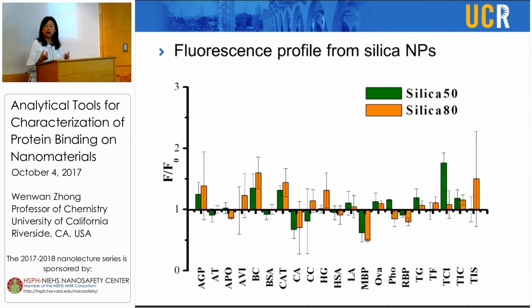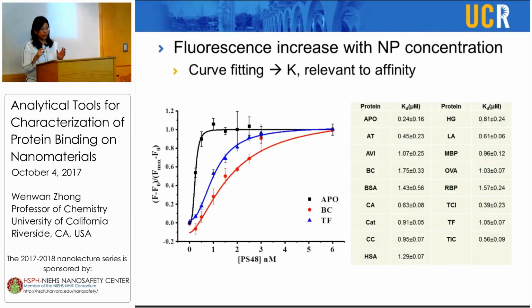So then we went on to study more about the interaction, the proteins that show high signal change when they bind to polystyrene particles. Because like I mentioned, a lot of this change could be due to conformational change of the protein. So that means our method can not only tell us what proteins could initially interact with each particle, but also what proteins may experience larger conformational change during the interaction. And here we are showing that the fluorescence signal change indeed can also tell us that certain changes could be relevant to the binding affinity.